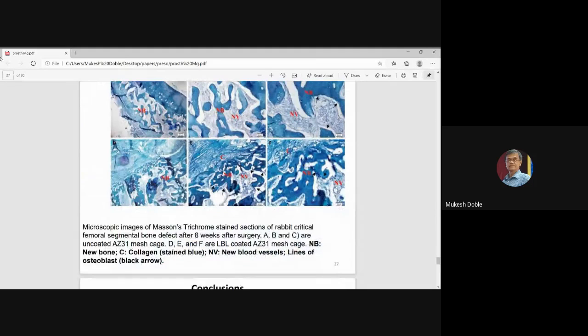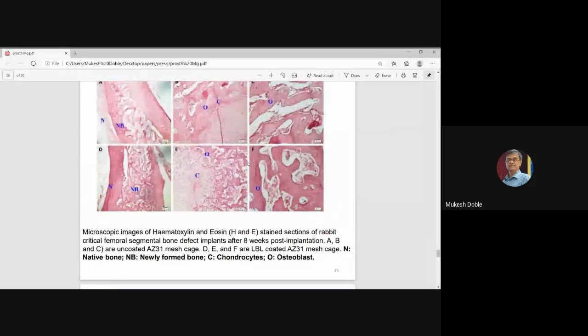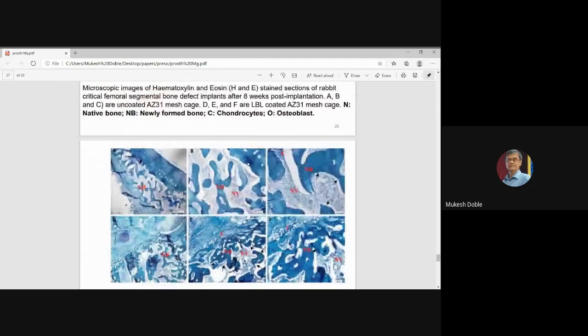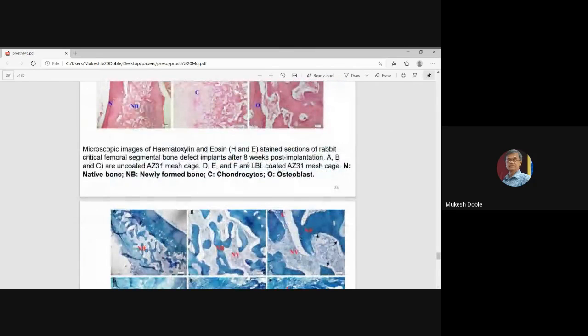Then we again look at the blood vessels, using some other type of assay. Again, we see collagen formation. Ultimately, collagen is very, very important in the bone. So collagen formation needs to be looked at, and also new blood vessels need to be looked at. As you can see, NV is there, quite a lot of NV is there, C is there, collagen. So the collagen matrix also starts growing. Newly formed blood vessels is also present in the coated AZ31. Okay, so we do see a lot of newly formed bone as well as newly formed blood vessels, and we see collagen deposition also. All these seem to be happening on the newly formed bone, especially with that which is coated with the AZ31 mesh cage.